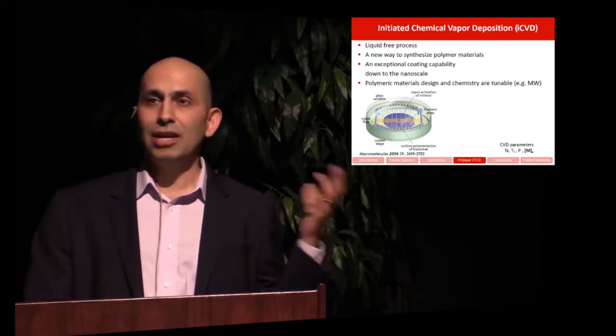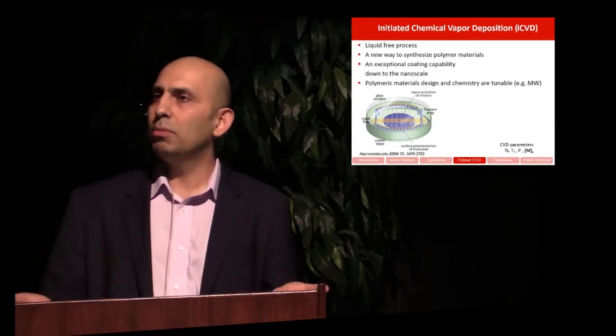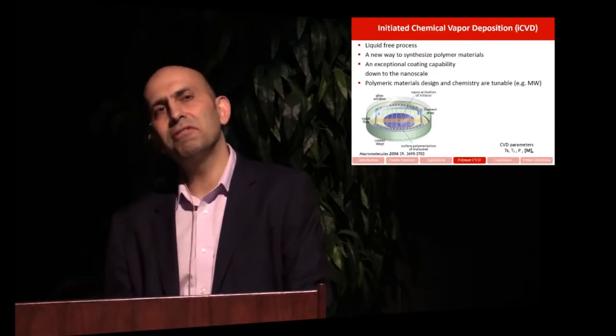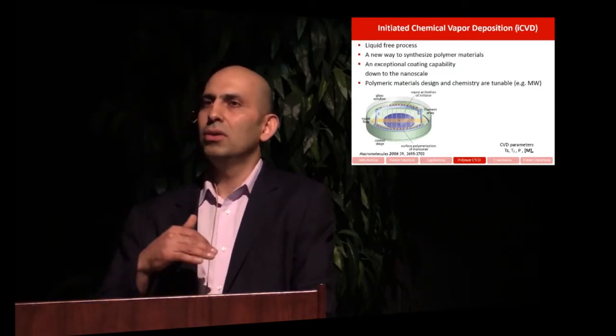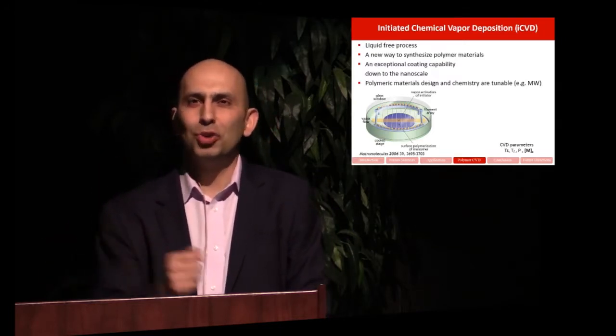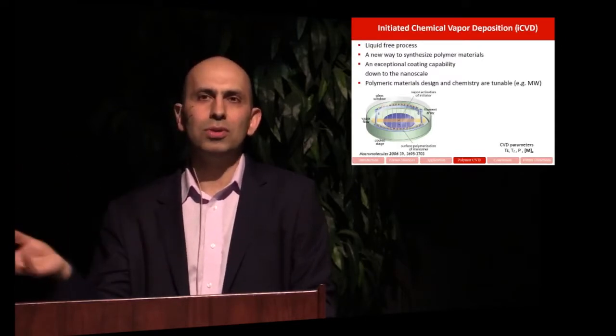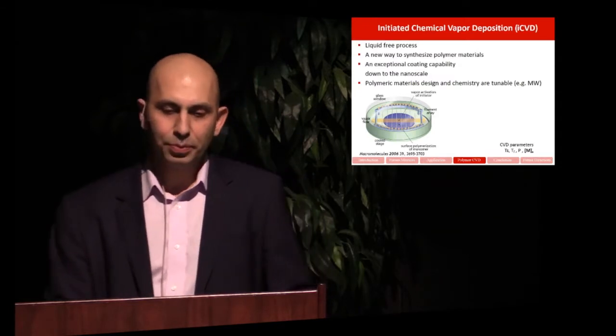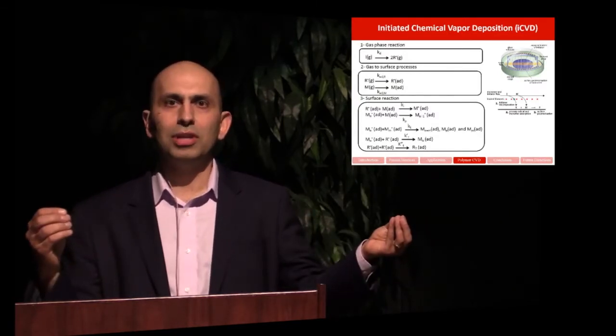The way it works, we bring a gaseous mixture of chemicals to a chamber and then initiate the polymerization at the surface. So basically, if you're going to coat a surface with different polymeric materials, you can just imagine putting that in the coating chamber, closing the door, and opening the lines so the monomers, the molecules that react, come, absorb on the surface and then react on the surface. Initially we break the initiator into a radical. The radical absorbs on the surface of the material that you wish to coat, and then that radical attacks a monomer, which is the single unit of a polymer, and forms a monomer radical. That monomer radical goes through a propagation reaction. Basically, it finds another monomer on the surface and reacts. Then another monomer attaches to it, and this continues until the radical terminates.